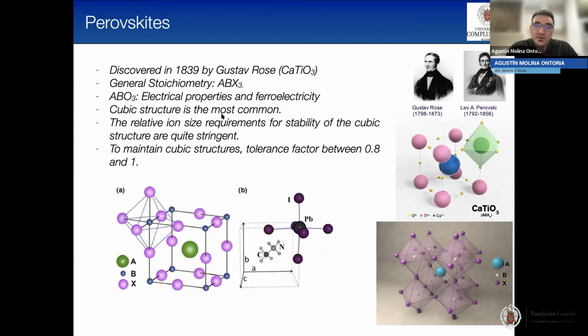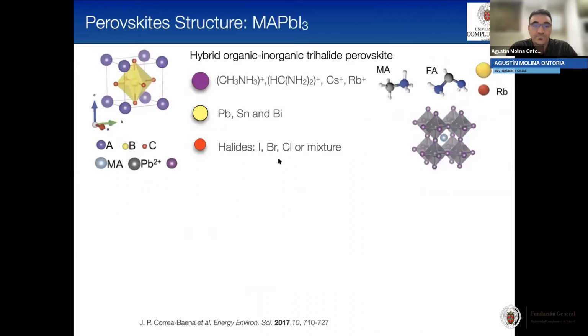This cubic structure is the one that is going to be active for photovoltaic applications. But this cubic structure is quite stringent to the relative ion size of the ions that made the perovskite. So to maintain this cubic structure, we have to keep the tolerance factor between 0.8 and 1. I will go into detail later on.